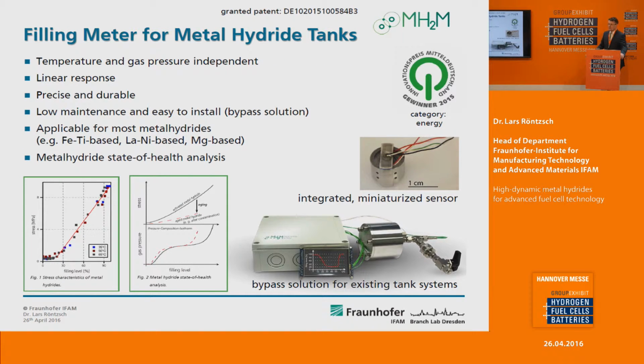A crucial problem with metal hydrides so far was determining the degree of filling of the pressure vessel, because usually one takes only the pressure inside such devices, which gives a very imprecise result. We have recently developed a sensor that relies on measuring a force inside the reaction zone, and thereby we get a linear relationship between the degree of filling and the force we measure. Thereby we can very dynamically and precisely determine the degree of filling, and we have more reliability in the use of the system.